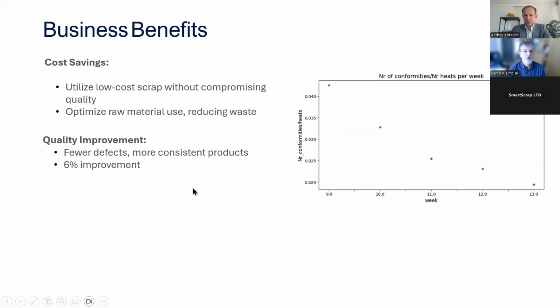Next is the quality improvement. So what we found is when applying the system, we have fewer defects with non-conformities of, for example, the copper content. You see here the application of the system, and we followed it for several weeks and found that the number of non-conformities decreased during the application of the system. So in the end, we had an improvement of around 6%.